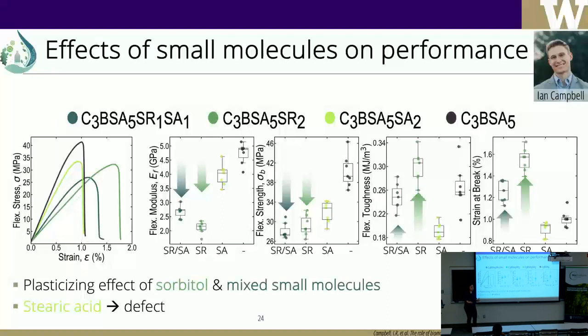So we're trying to understand now the small sugars with the fatty acids, what is their role? In this case, the first data point that you see has both of the small molecules. The second bin has only sorbitol. The other has only stearic acid, so 20%, 20%, and here 10 and 10. And here you don't have small molecules. You only have cellulose and protein mixed together. So you see that our modulus and strength are highest when we don't have small molecules, when we have our strong fiber, cellulose, and some matrix, the protein, working as a fiber composite, basically. And then when we start introducing the small molecules, in particular sorbitol, we see a classic plasticization behavior where we have an increase in our strain at break.